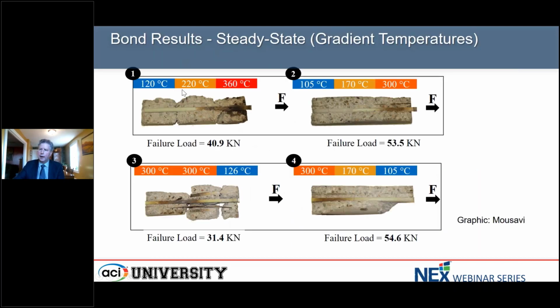And you can see what happens here. So in this case, we're pulling on this end and we have it very hot, that's what's normally expected in a fire scenario like what we had in our fire test, and then it cools down over this region, but it's still at 120, that's over water boiling temperatures we have here, but you can see that even visually it's not affected so much here. And so we can still rely somewhat on that bond.